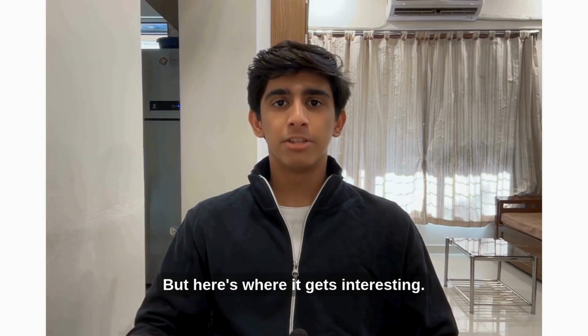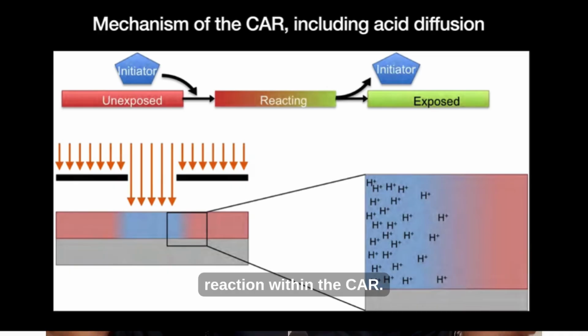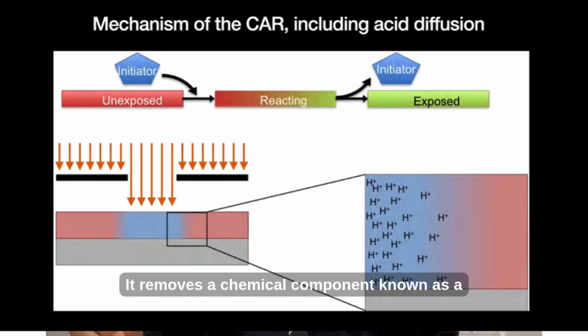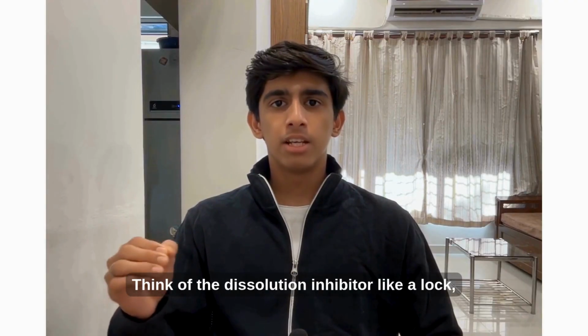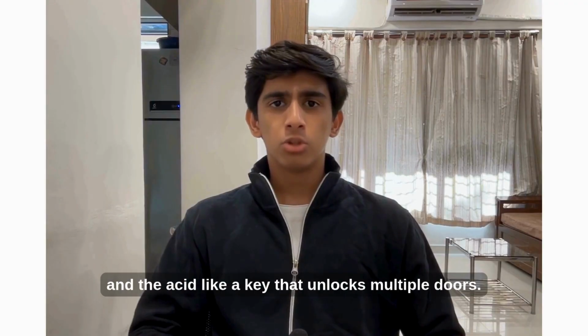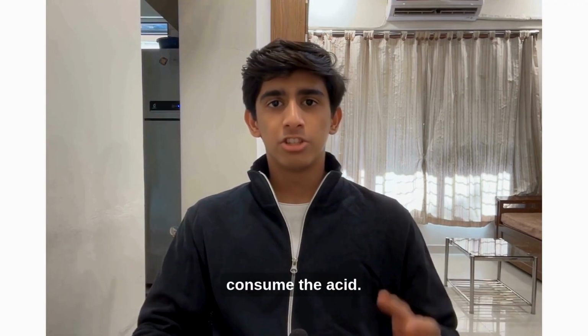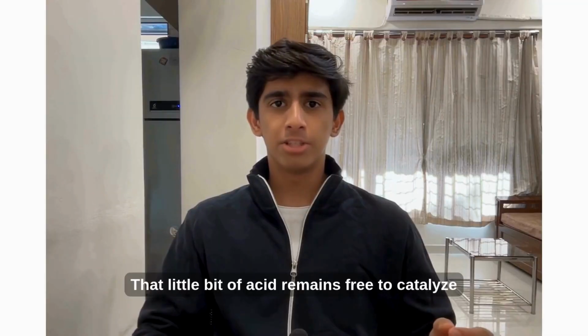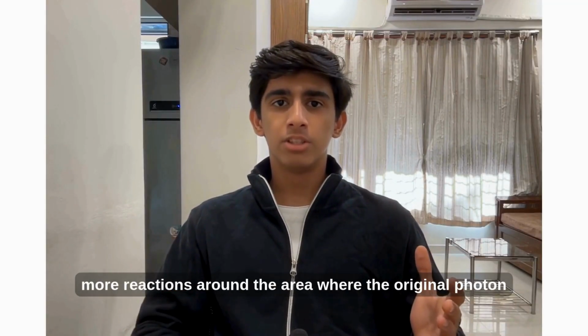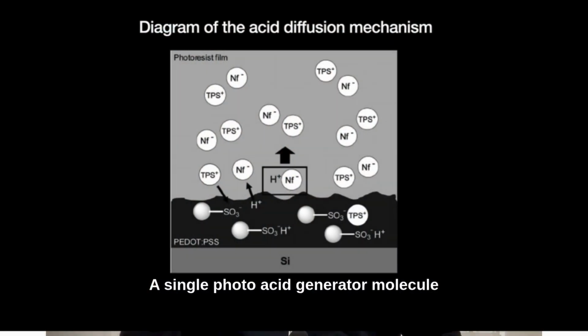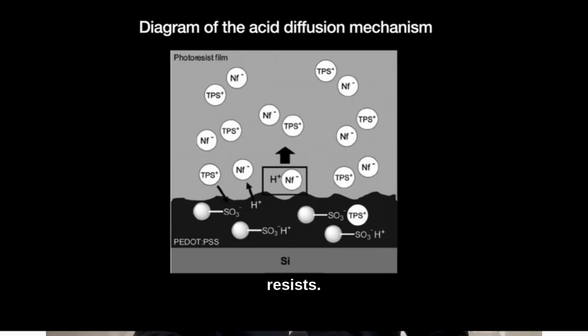But here's where it gets interesting. This acid goes on to catalyze another reaction within the CAR. It removes a chemical component known as a dissolution inhibitor that previously blocked the CAR's ability to dissolve in developer liquid. Think of the dissolution inhibitor like a lock, and the acid like a key that unlocks multiple doors. The really clever part is that this reaction doesn't consume the acid. That little bit of acid remains free to catalyze more reactions around the area where the original photon hit. A single photoacid generator molecule can catalyze hundreds of reactions. This is the amplification in chemically amplified resists. One photon creates one bit of acid, but that acid can trigger hundreds of chemical changes.